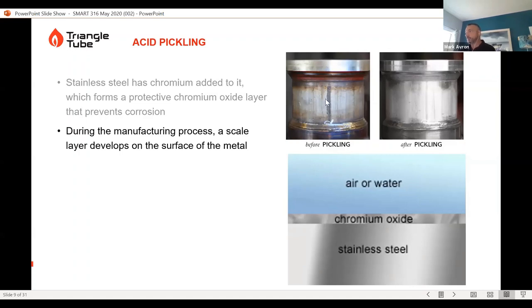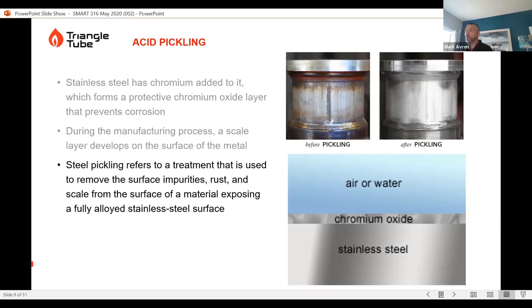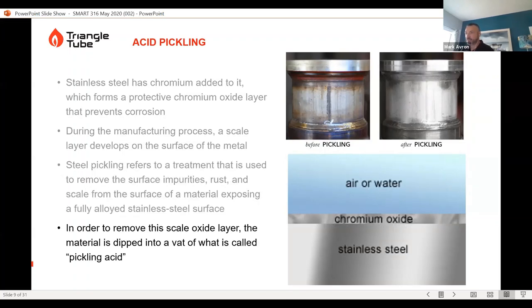In the picture on the top left-hand side, you see the before pickling. This is after this piece was welded. You can see what it looks like. There are contaminants that have taken away that chromium oxide layer and produced this scale layer. After pickling, we completely cleaned up the material, and this chromium oxide layer will naturally reproduce itself. Steel pickling refers to the treatment used to remove surface impurities, rust, and scale from the surface of the material, exposing a fully alloyed stainless steel surface.